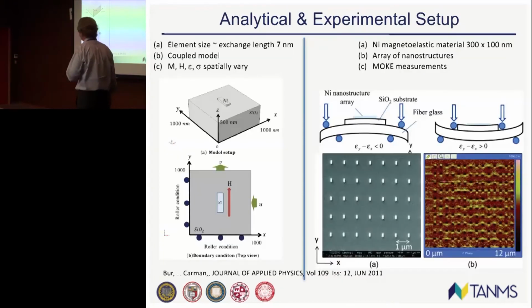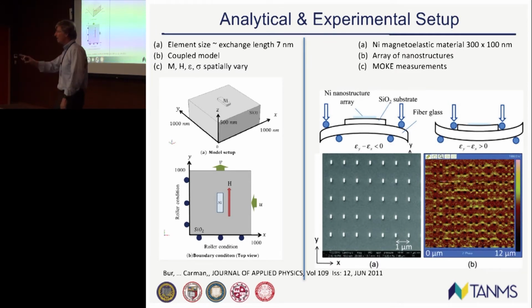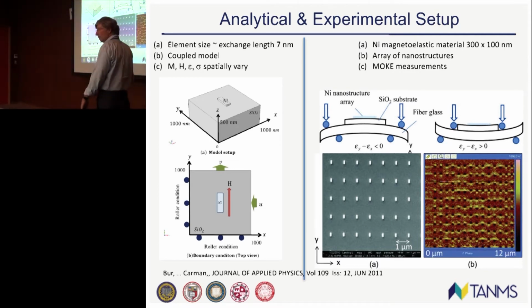Let's take a look. What we did is we tried to go out and validate a code we developed in-house. So what we did is we first modeled a nickel single domain structure. How big was the nickel? About 100 nanometers. It was on a clamped substrate, silicon dioxide. And we actually said, well, how much can we change its coercive field? And what we did is we actually went out and did experiments.